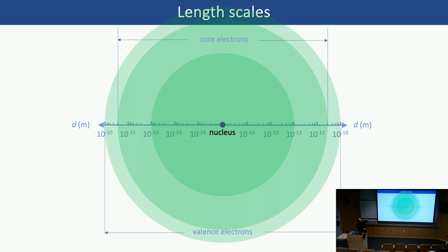And when you fly a little bit closer to the nucleus, with a more precise range in target, you could fly very close to the nucleus. If it hits this target, it could transfer about 1 eV to the target atom. The way you could transfer that energy is through Coulomb interaction. The electron has negative charge, your nucleus has positive charge. When it moves around, it transfers a certain amount of energy and momentum. So when you fly into this picometer range, 1 eV of energy could be transferred.